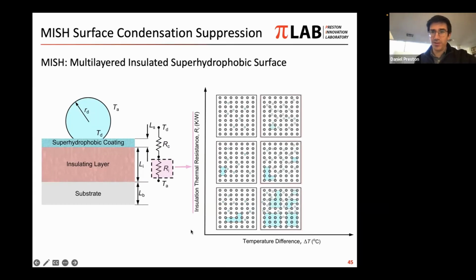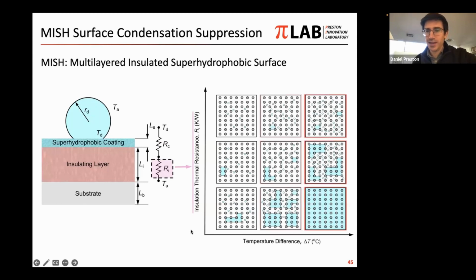But at higher temperature differences, this can become quite important in the sense that if we don't have any insulating layer, we might fully fill in the structures on the surface and get a high level of adhesion. But if we can prevent the heat transfer and the evaporation and recondensation from occurring, we may significantly limit that added adhesion and maintain the superhydrophobicity.